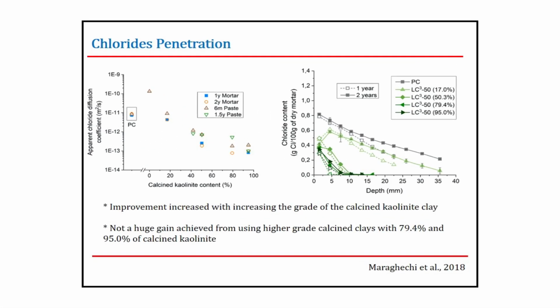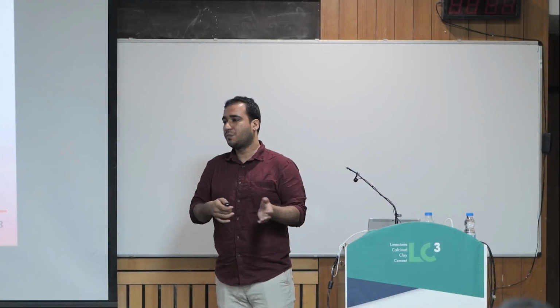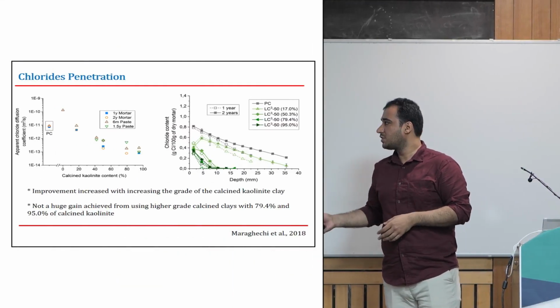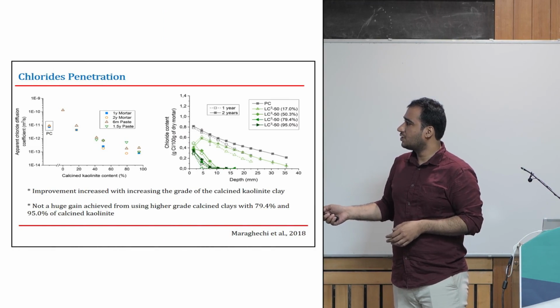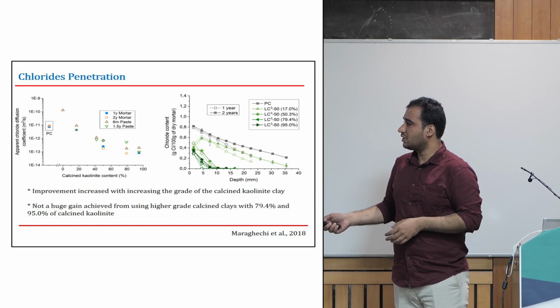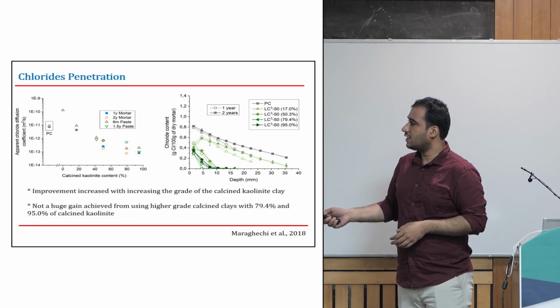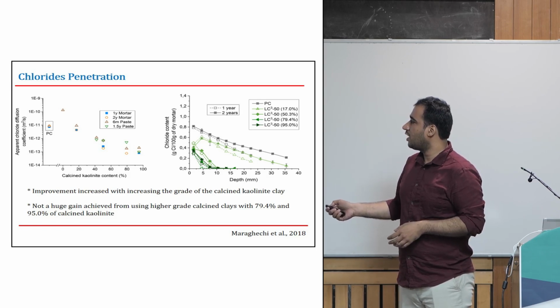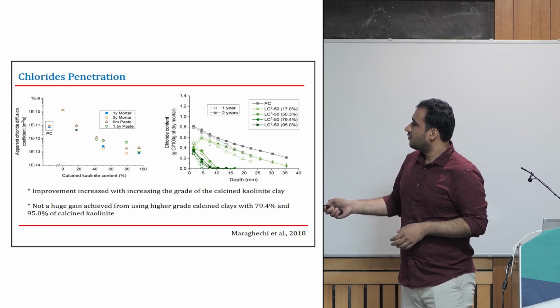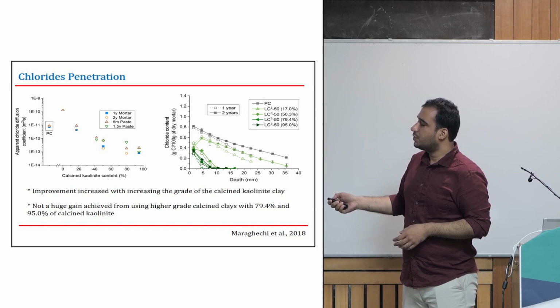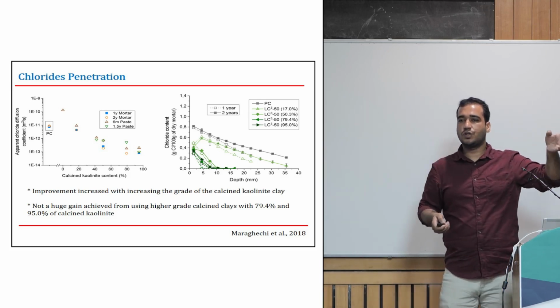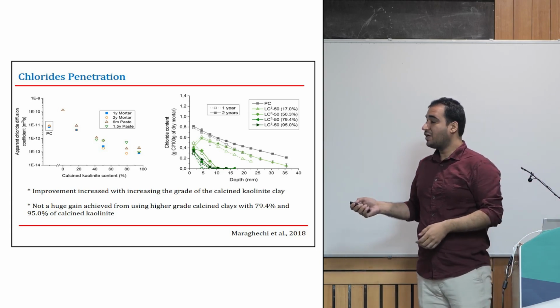These are typical chloride penetration profiles compared for OPC and the cements blended with LC3 having different kaolinite content. These formulations are with 50% LC3, like 50% clinker, and the remaining 50% calcined clay, limestone, and gypsum. As you can see, compared to OPC, the initial one is quite high. That's not LC3. That's where the calcined clay is totally replaced with quartz. But once you start blending the calcined clay, you start seeing a decrease in the apparent diffusion coefficient. And if you compare the chloride profile after 2 years, you see that for LC3-79 and 50, it's much lower compared to the OPC systems. So the performance which was not as good in terms of carbonation, here it's quite a different view.